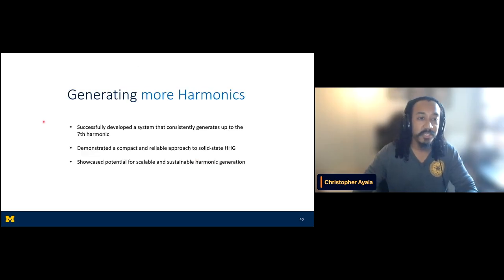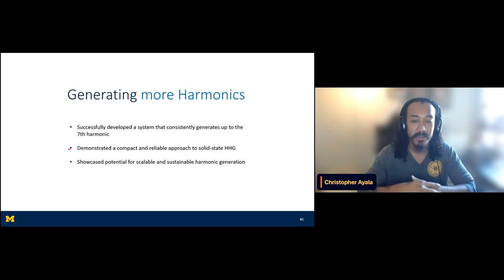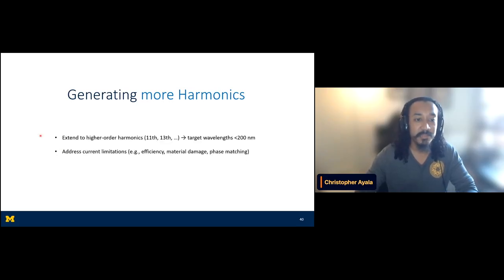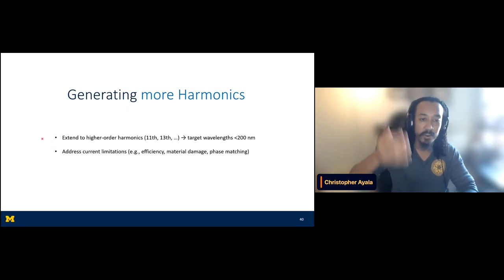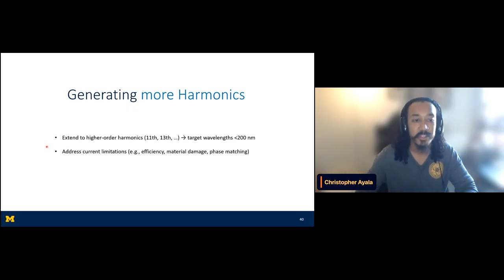So in conclusion, at least now we're able to fully develop a system that consistently generates up to the 7th harmonic. Hopefully we can push it further. I've demonstrated a compact and reliable approach to generate these high harmonics, and we have showcased the potential for scalable and sustainable harmonic generation. The next steps that we aim to achieve, hopefully soon, is to extend these higher order harmonics to the 11th, 13th, and so on, which would be wavelengths that are under 200 nanometers in the vacuum ultraviolet, and hopefully address our current limitations, being the efficiency.